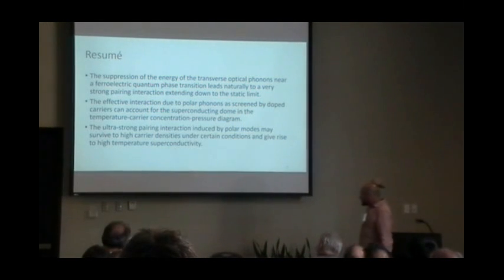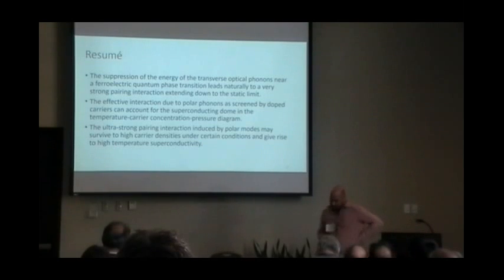So this means, to summarize, that the suppression of the transverse optical phonons near the ferroelectric quantum phase transition leads naturally to a very strong pairing interaction for the electrons. So from that model, you get superconductivity naturally without putting too much in. And the effective interaction due to the polar phonons is easily screened by putting in electrons.